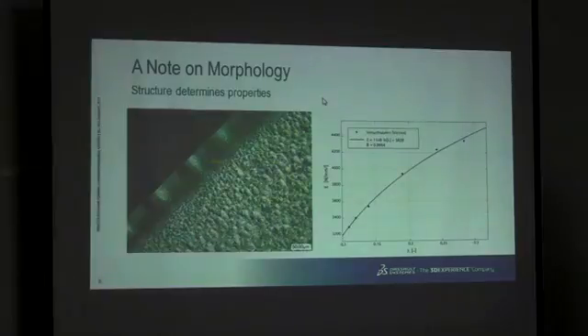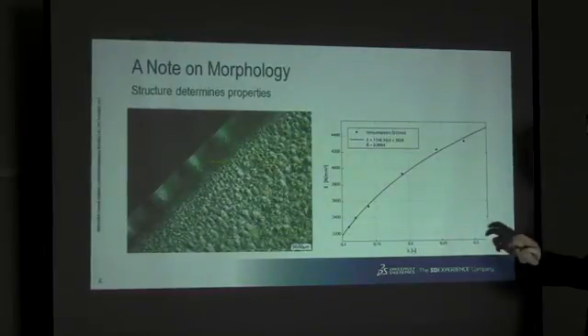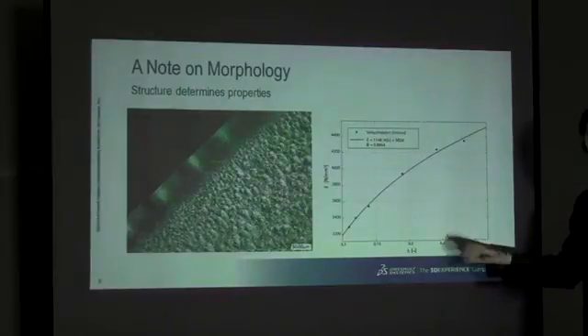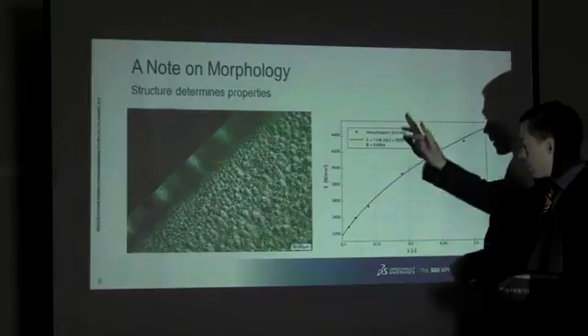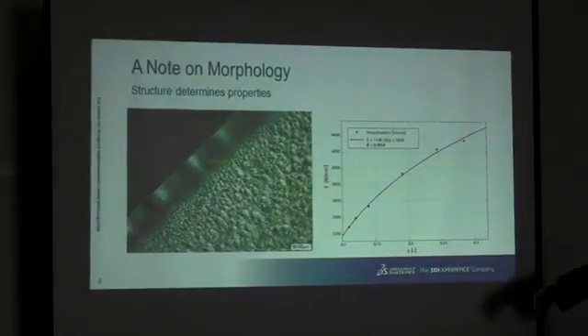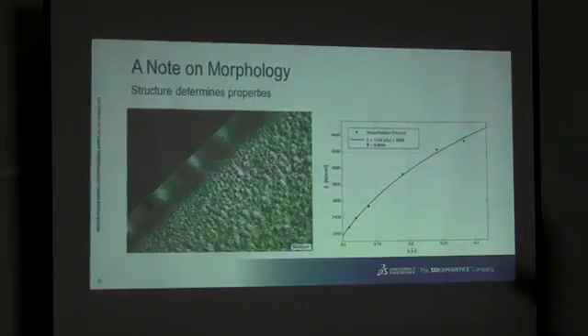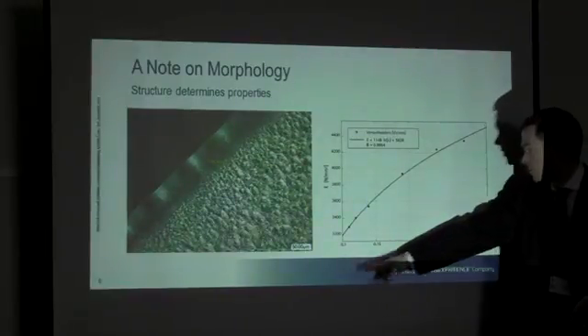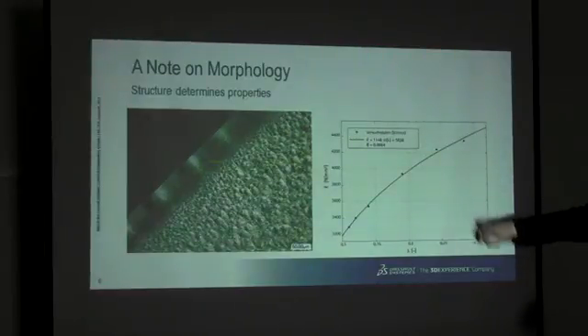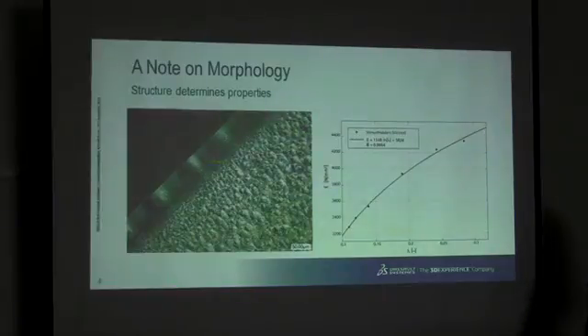The other important variable often used in semi-crystalline polymers is the degree of crystallization. And this is a diagram that shows the apparent Young's modulus. There is no Young's modulus for plastics, so let's just leave it at that. This is a secant modulus taken at some specific strain. And this is the degree of crystallization. Now, they're called semi-crystalline, but that doesn't mean they can all reach 50% crystallinity. In fact, the degree of crystallinity can vary anywhere from 20% up to 85%, depending on what the polymer is. Now what you see here is a non-linear relationship, so that with increasing degree of crystallinity, the modulus increases, but there is obviously a peak at some point. These are also things to bear in mind.